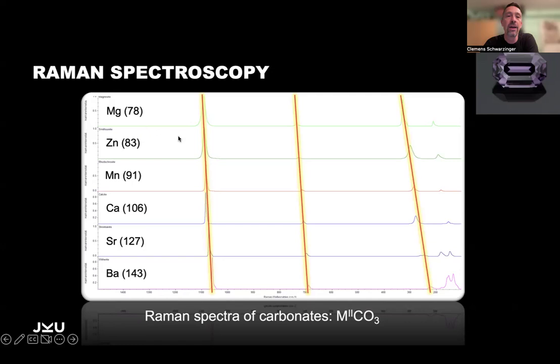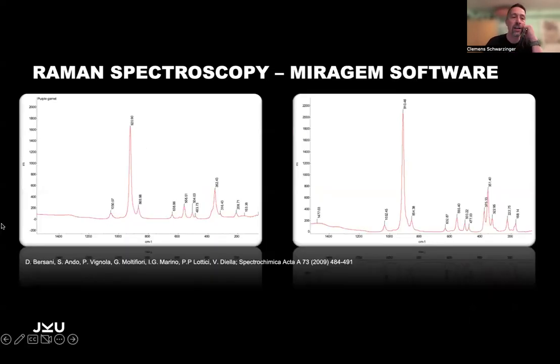And you can just calculate, from the position of one of these peaks, the average diameter of the cation that is inside. The problem now comes if you have a mixture of manganese and magnesium, it may also be a zinc inside. So this is something that you cannot differentiate, but for garnet, it works pretty well. Because luckily, my Italian colleague, Danilo Bersani, has written with a couple of his colleagues a software that is called MIRAGEM. And this MIRAGEM now takes a spectrum. You have to put in a couple of numbers: where the peaks are, how many peaks there are. And then you can differentiate these 2 garnet spectra.